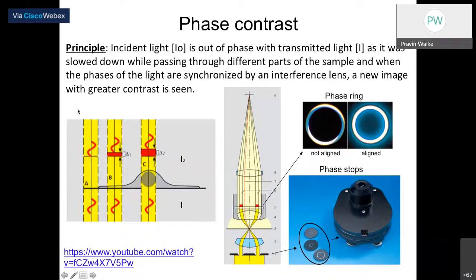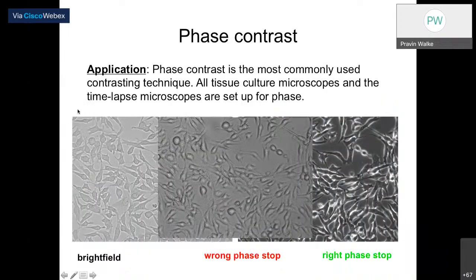Okay, so as we have seen some of the images before, now let's have a look at the phase contrast images and just get a feel for how phase contrast is very helpful in the case of the microscope, right? So here you see the bright field imaging, where this first image is showing you the bright field imaging. But if you do not have good phase synchronization, you can see here the wrong phase stop, where it is very difficult for you to see the image properly. But at the same time, if you have the right phase stop, then you can easily see this image, which is completely overlapping with the bright field imaging, right?